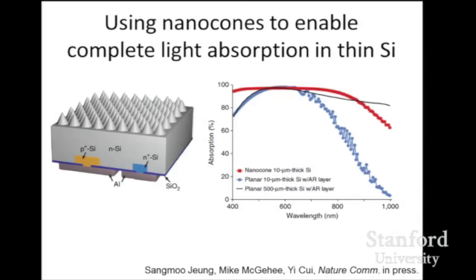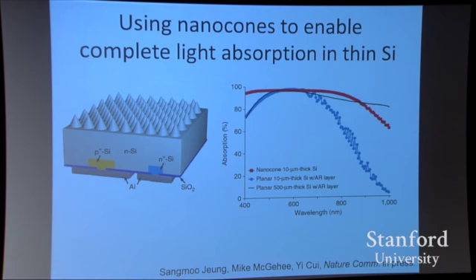Yi Cui's group has done work in a new kind of light trapping. Conventionally, you etch pyramids into the silicon, but when you have a 10 micron thick wafer and you want to etch several micron thick pyramids into it, sometimes stress can cause the whole thing to curve. And so it could be better to have these nanocones that cause the refractive index to gradually change. And for that reason, the light doesn't reflect. And in this paper that will come out soon in Nature Communications, Sangmoo Jeung showed that you can get essentially 100% light absorption in these 10 micron thick solar cells. But the real challenge is just going to be the manufacturing and figuring out how to do this at high volume and low cost.